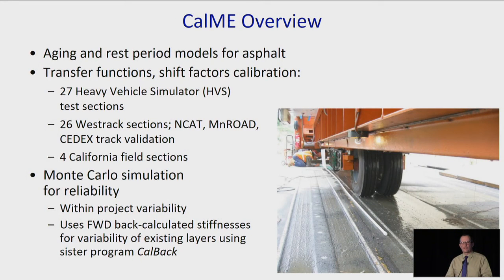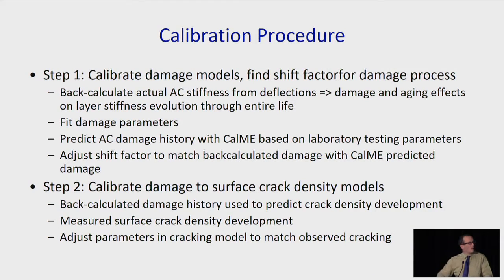A fundamental part of this was the development at the same time of a back calculation program, because we primarily are dealing with existing pavements. We want to rely on deflection back calculation to characterize those, both in terms of variability of the underlying structure as well as the material properties. So CalBack was invented as a sister program that goes with that. And CalBack loads directly up into CalME, gives you your material properties, and also gives your variance of the stiffness, which is considered in the Monte Carlo simulation.